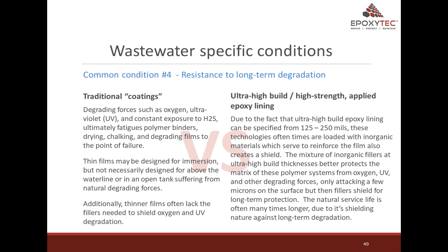Common condition number 4, resistance to long-term degradation. Traditional coatings. Degrading forces such as oxygen, ultraviolet, and constant exposure to H2S ultimately fatigue polymer binders, drying, chalking, and degrading films to the point of failure. Thin films may be designed for immersion, but not necessarily designed for the above waterline or an open tank suffering from natural degrading forces. Additionally, thinner films often lack fillers needed to shield oxygen and UV degradation.